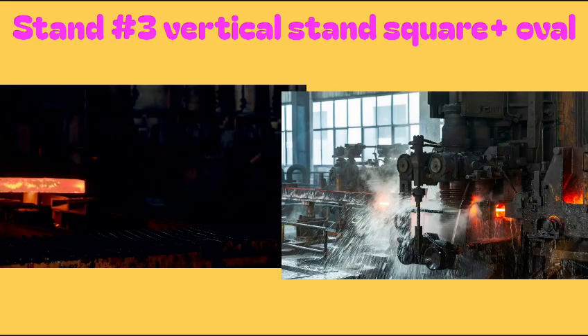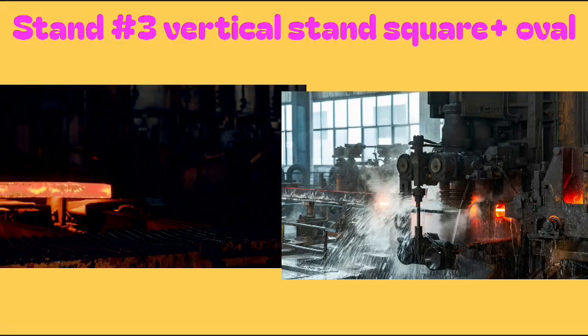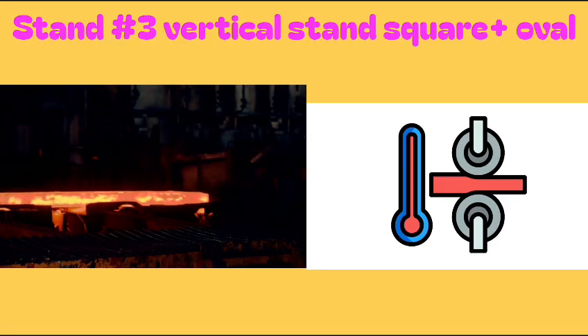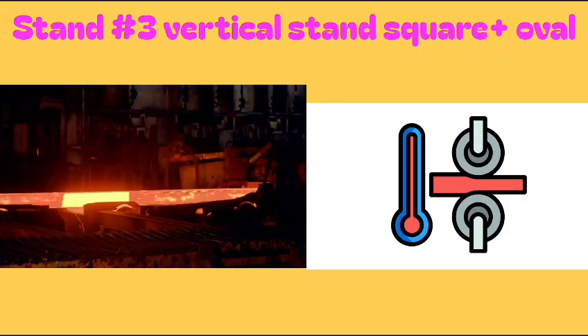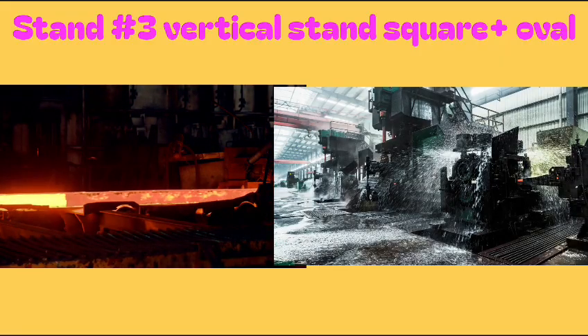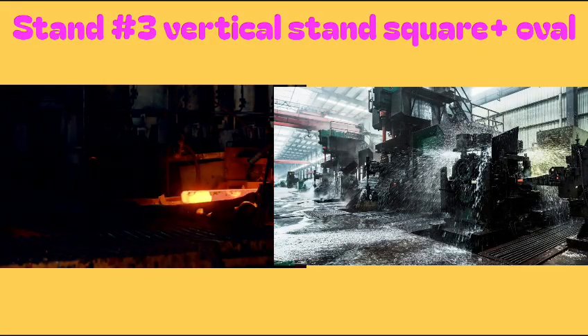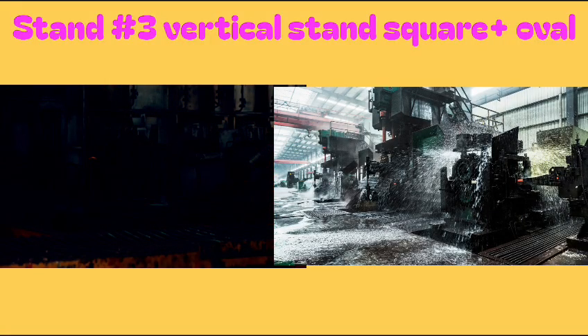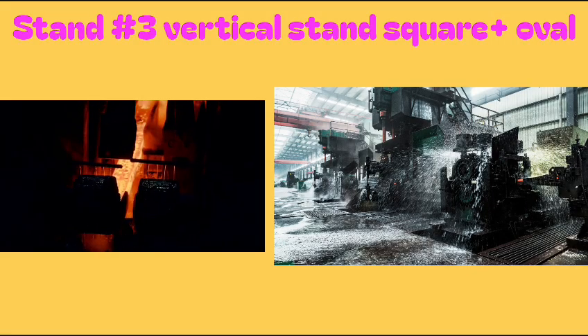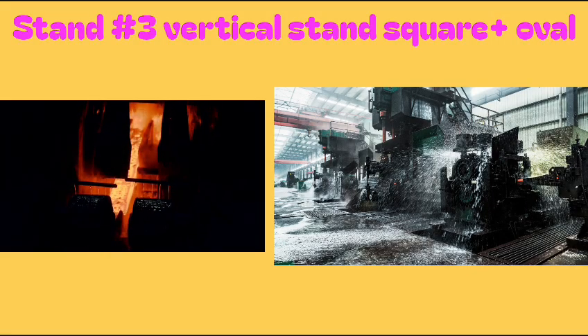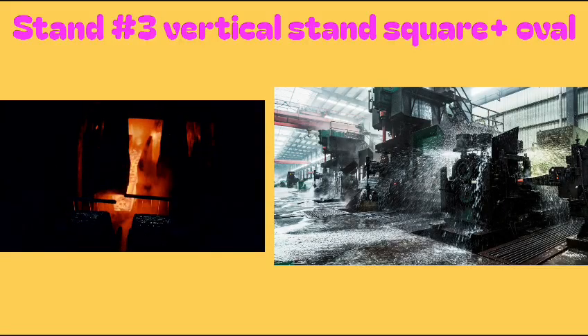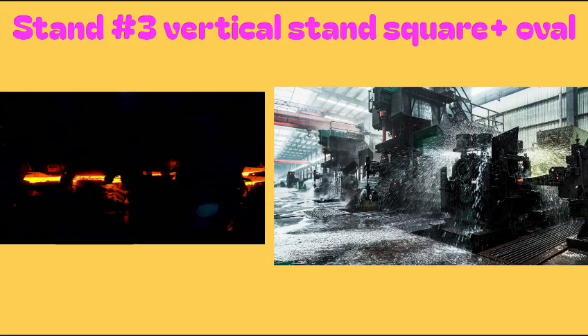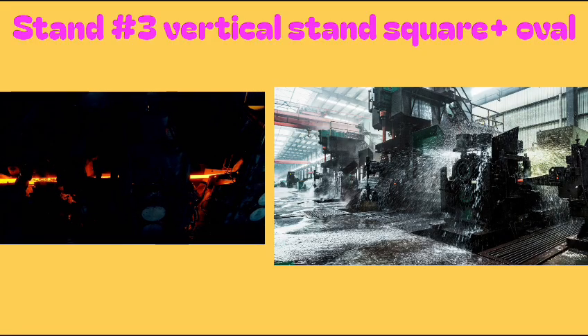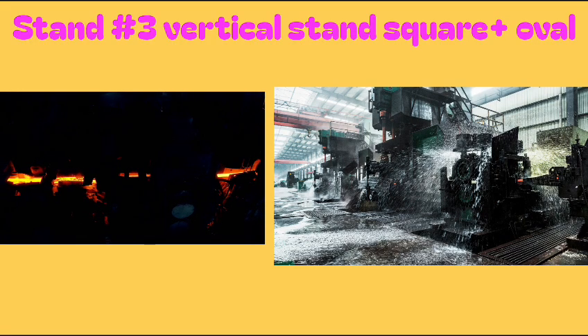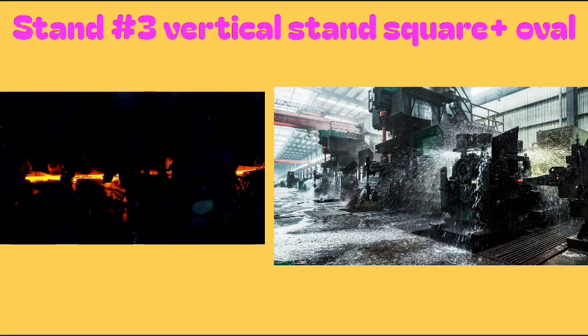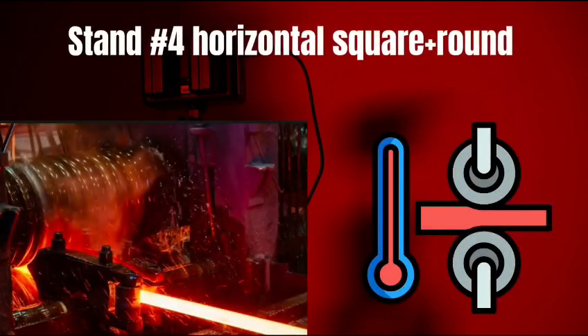Stand number 3, vertical stand. The billet passes through the two vertical rollers, both rotating in opposite directions. The hot billet passes through the center groove, and because of the rotation the rollers grip and pull the billet forward. The billet size reduces from 95 mm to 80 mm, a reduction of 15 mm. The force is applied to the sides. The billet shape is converted from square to oval.